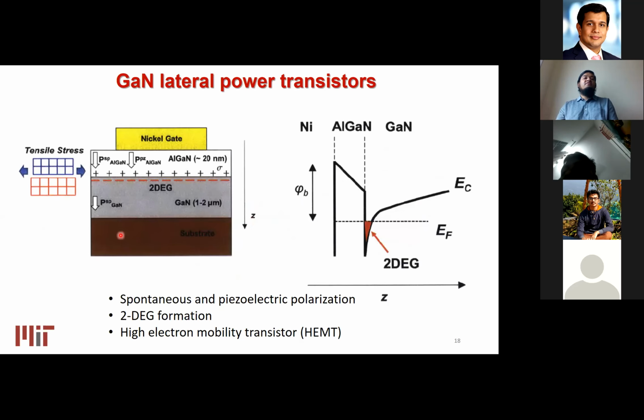So here on the left, we're showing how a typical gallium nitride heterostructure looks. This grayish region is, say, 1 to 2 micrometer thick gallium nitride, and if we grow a very thin layer, say 20 nanometer, of a ternary alloy, which is aluminum gallium nitride, it's a combination between gallium nitride and aluminum nitride.